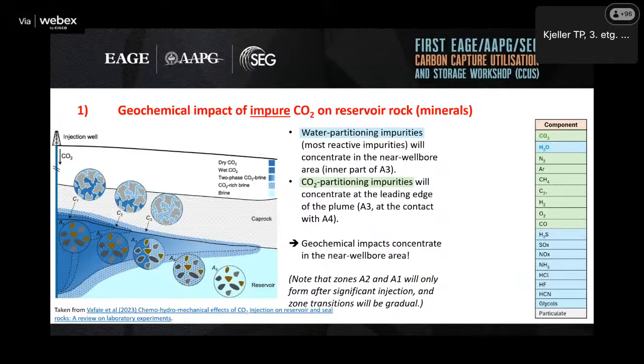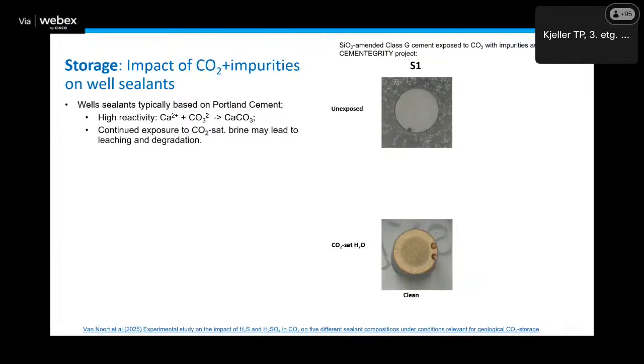The caprock is similar, but caprock overall is very tight, so these reactions are limited in how far they can penetrate, as the CO2 doesn't penetrate deep. But as I said, the cement sealants around the well may be a much more vulnerable spot, because they are typically based on Portland cement, which has very high reactivity with CO2, forming calcite. And if you have continued exposure to CO2 saturated brine, this calcite may subsequently dissolve, and then you get proper degradation. So we see here some research from the Cementegrity project.